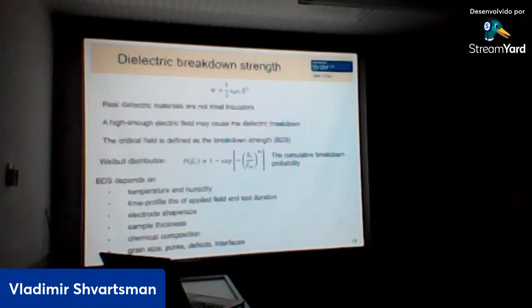How is it measured? Typically, we take many materials, bring them to the breakdown event, estimate the electric field where breakdown takes place, and then make a so-called Weibull distribution. From this Weibull distribution, we estimate the parameter EW, which is our breakdown strength. And breakdown strength depends on many parameters: temperature and humidity, time profile of the applied field and test duration, size and shape of the electrode, sample thickness, chemical composition, and microstructure of the material, like grain size, pores, defects, interfaces, etc.